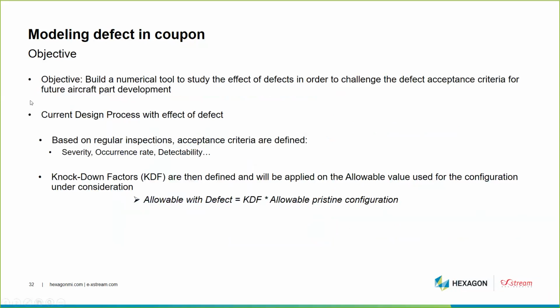So the thing is, we have to see how it's done today. When we have to deal with effect of defect in the current design process, we use a knockdown factor. The knockdown factor is a coefficient that is applied to the allowable value obtained on a pristine configuration, and by multiplying this knockdown factor by this allowable, we obtain the allowable with defect. But today, the value of this knockdown factor has been identified based on regular inspection, and this value has been defined based on the severity, occurrence rate, detectability. So it's a bit of an empirical way to determine this knockdown factor. That's why we try to propose a numerical tool to refine the determination of this knockdown factor.